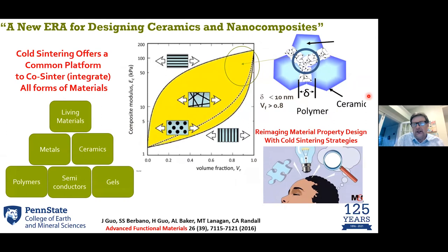More than just ceramics, what this offers with this basically severe reduction of the processing temperature of a ceramic, we now can push the ceramic processing temperature in the domain of where we do polymers, and polymerizations, cross-linking, and flow processes with polymers. So now you can actually make new types of composites where you can put small amounts of polymer in the grain boundaries of ceramic materials to develop completely new nanocomposites with new types of properties. You can combine metals, you can combine semiconductors, gels, as we have in some of the battery materials. And in fact, I have a colleague in England even looking to incorporate living materials into the ceramic matrix at lower temperatures.